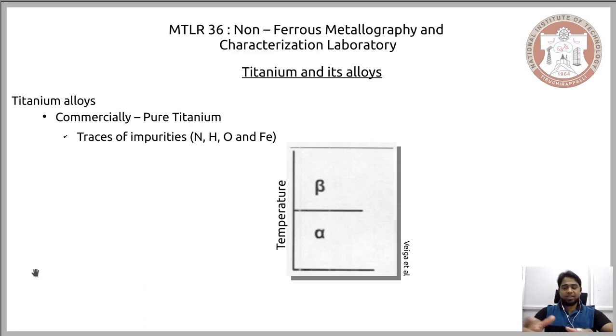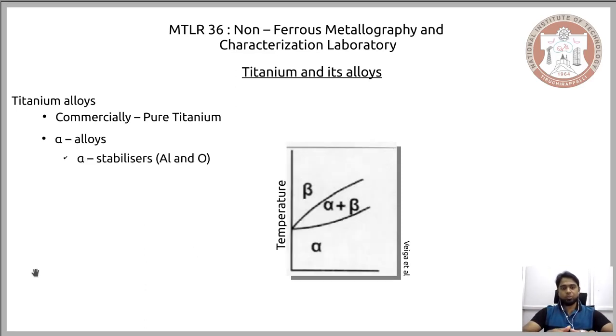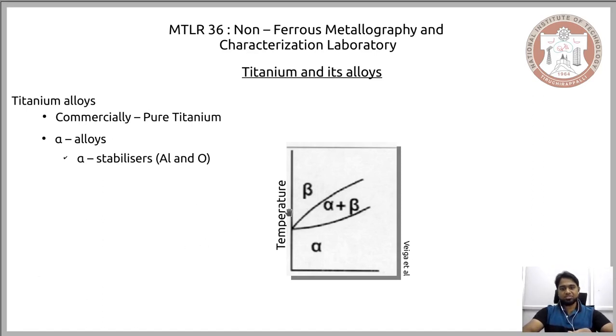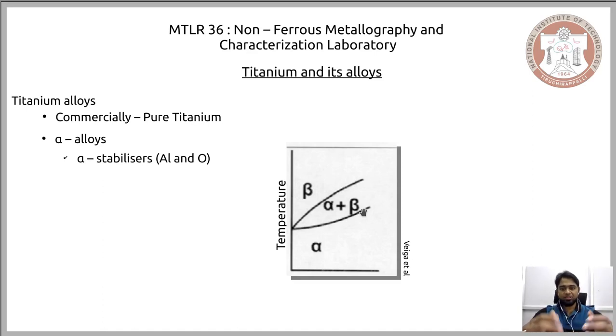The first category of titanium alloys is the alpha alloys. The stability of alpha alloys at room temperature is increased by adding alpha stabilizers such as aluminum and oxygen. Looking at the phase diagram, these alpha stabilizers increase the transus temperature. Alpha alloys characteristically comprise alloying elements that are alpha stabilizers, and what they do is raise this transus temperature.